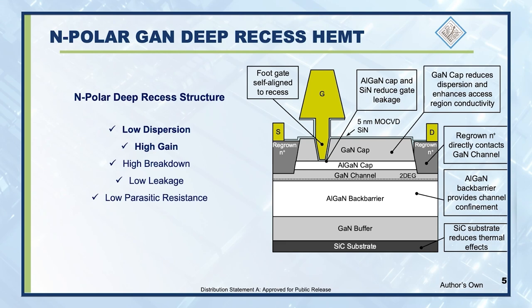This gallium nitride cap reduces dispersion and simultaneously, because of the physics of polarization, increases the conductivity of the channel underneath. So simultaneously, you get a very low parasitic resistance in the device and you get low dispersion because of this cap. Also, because you have the placement of the gate very close to the channel, you have very high gain, both because of the proximity of the gate to the two-dimensional electron gas, and also the exceptional transport properties of the two-dimensional electron gas.